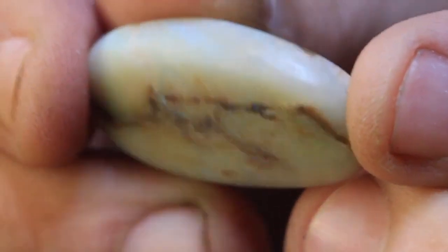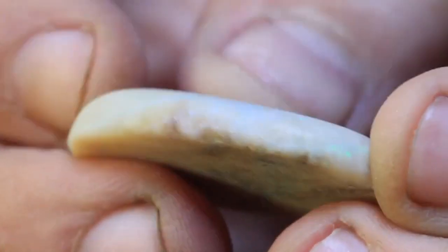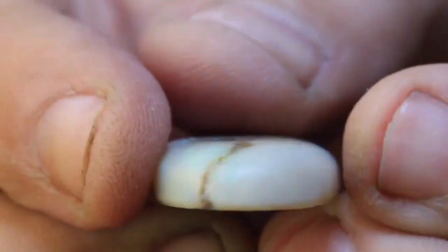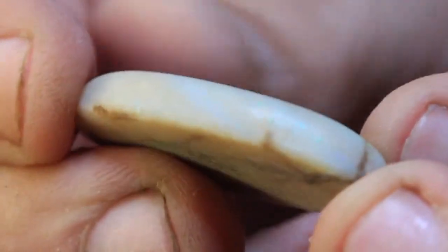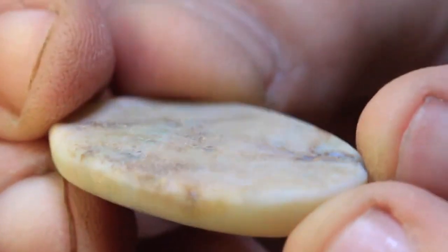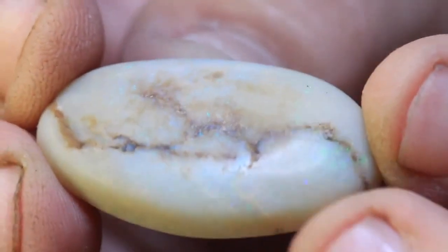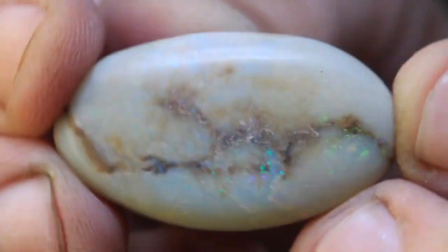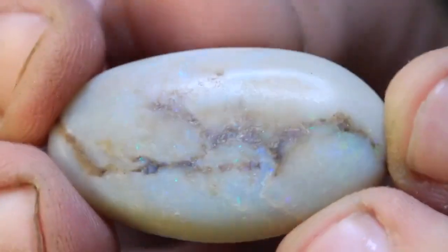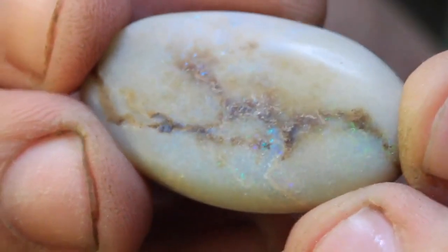Alright, so before it goes into treatment, this is what it should look like. You see that bottom edge has been taken off. It's not very sharp anymore. There's no wax or anything on the bottom. It's not polished. The top has a very dull polish on it. You don't want it too polished. You want those pores nice and open so that whenever we put it in the treatment, it'll soak that sugar up. If you polish it too much, it won't treat.